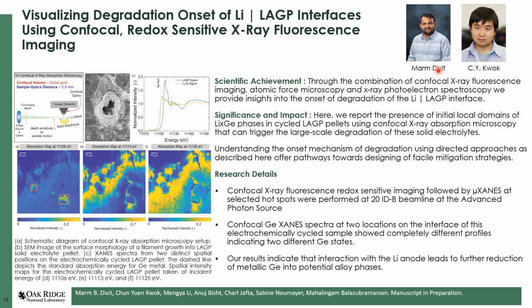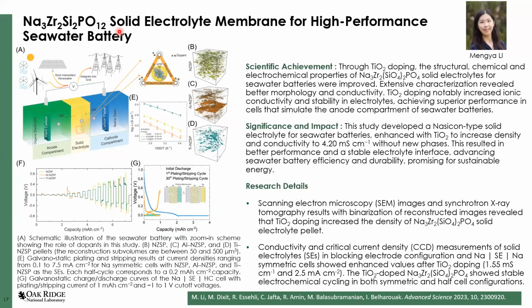So in order to do that, one has to figure out ways by which we can understand interfaces and see how events take place. Recently we started using confocal, micron-scale sensitivity X-ray fluorescence imaging at the APS, where we are able to look at the nucleation events between a solid electrolyte and lithium. This should hopefully allow us to expand this to an operating solid state battery, where we can understand how detrimental events take place at this interface and hopefully come up with mitigation strategies for it.